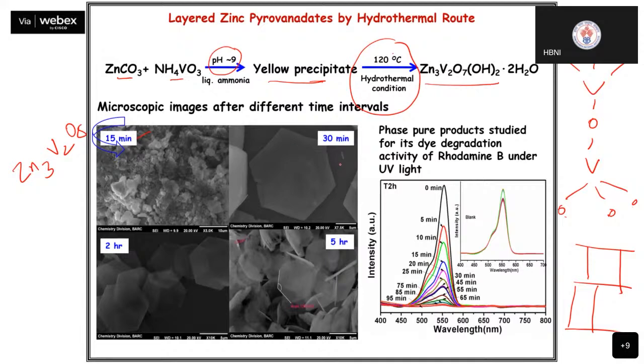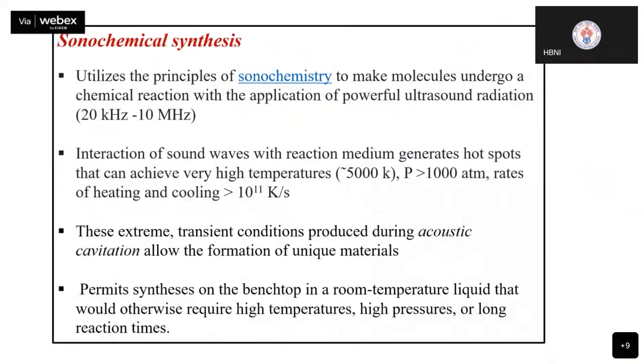After 30 minutes, it gave me these nice hexagons. This was the best product that I achieved after 2 hours. And after 5 hours, again that hexagonal morphology is there, but as you can see, my hexagonal particles have started breaking up a little. This was a very interesting experiment, and these are probably the best SEM images that I have received for any of my products. Okay, so this is how we plan. I'll just rush up a little.